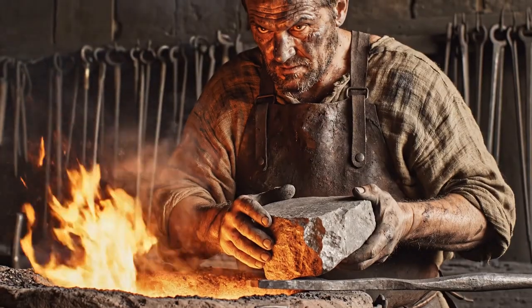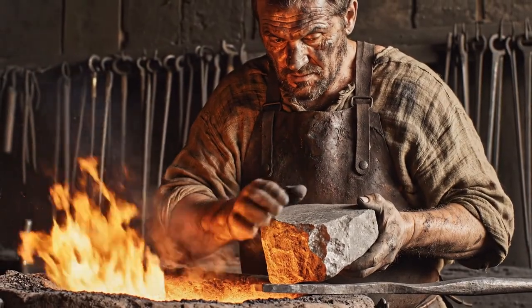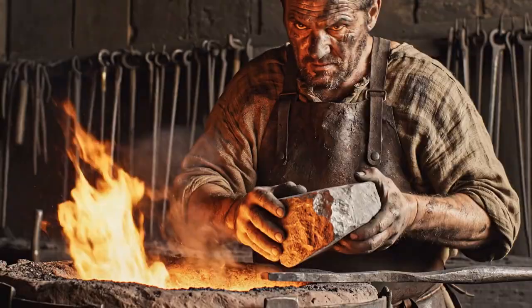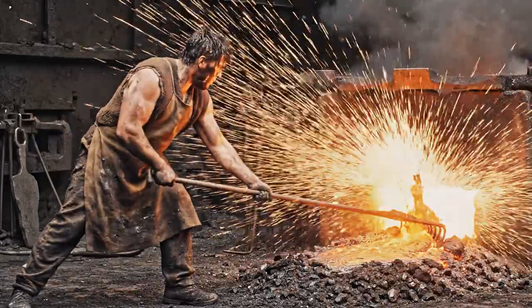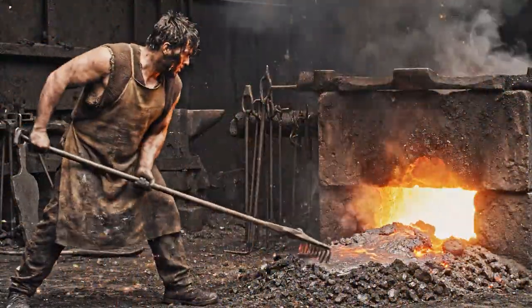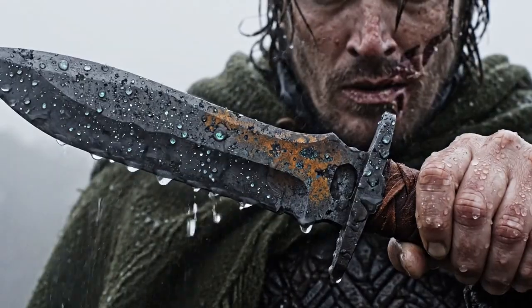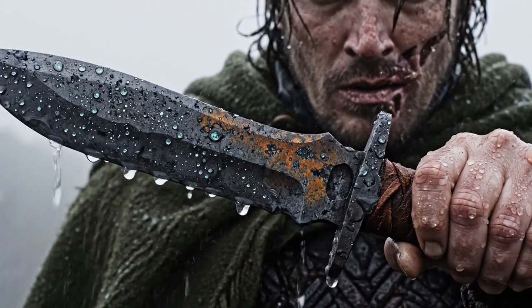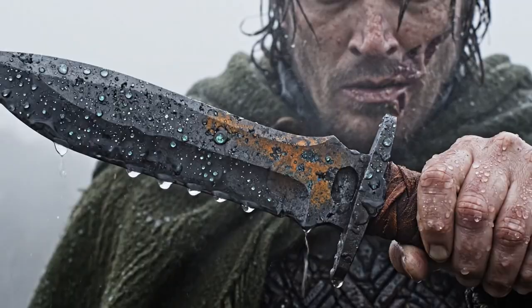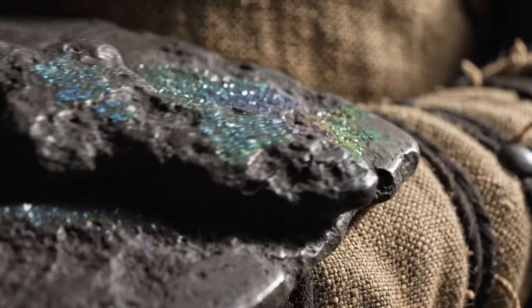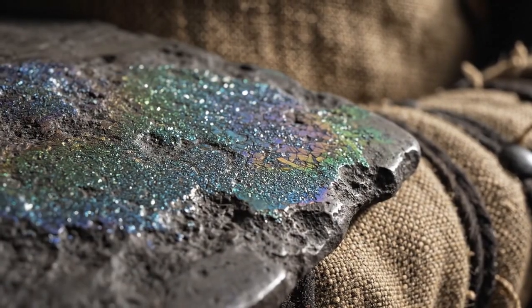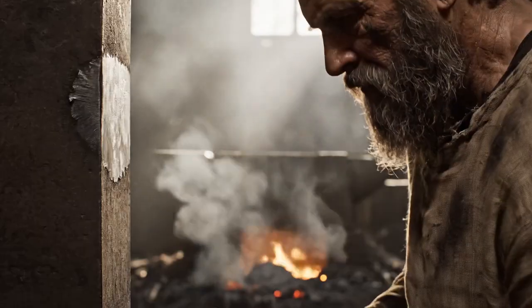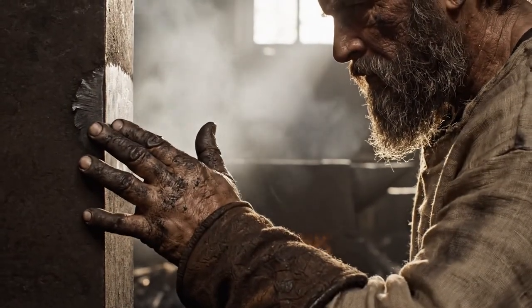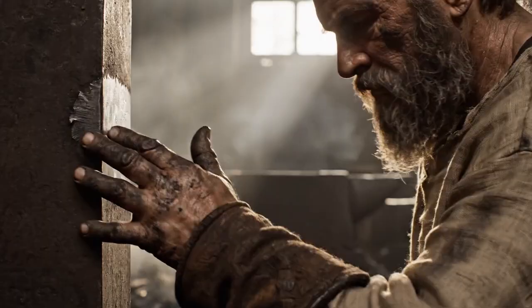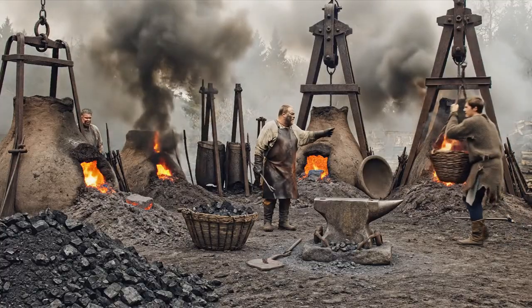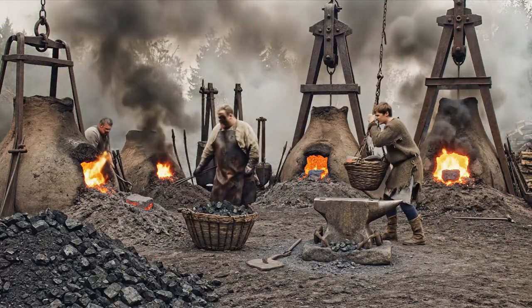In modern blast furnaces, limestone is used to produce pig iron, and in this process, most of the phosphorus is carried away by the slag. The Indian blacksmiths, by omitting the limestone, inadvertently preserved the phosphorus in the metal, and this phosphorus reacts with moisture and air over time to form crystalline iron phosphate, a compound that works as an additional barrier against corrosion. The protective film has grown only 1/20th of a millimeter in 1,600 years.